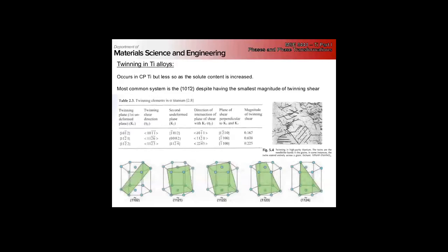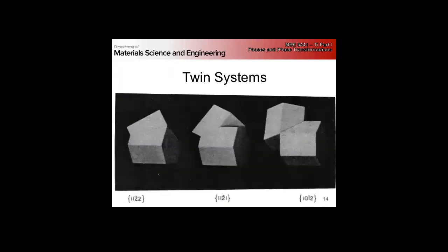Basically, you can think of the twinning as a rotation here. So our C-axis becomes aligned almost 90 degrees. It's like an 88-degree rotation, right? We can sort of visualize that here, right? Here's our twin plane. Here's the parent. Here's the twin, and we can see that we have roughly 90-degree reorientation of our C-axis. So what's that going to do to our properties?